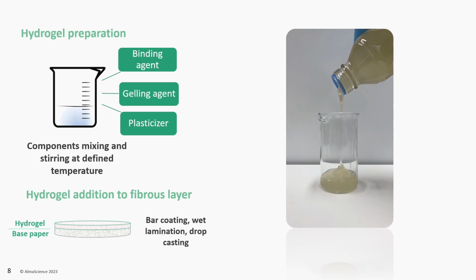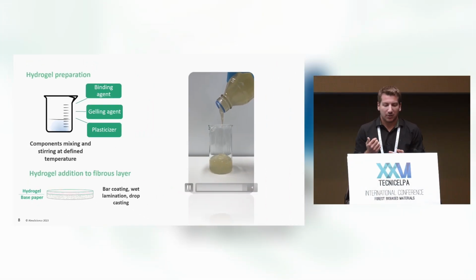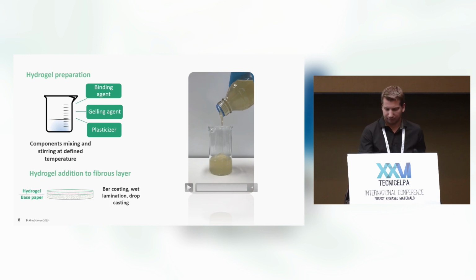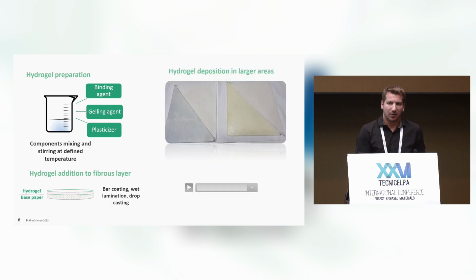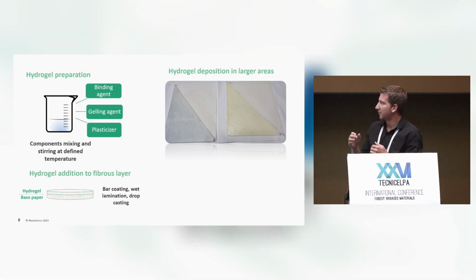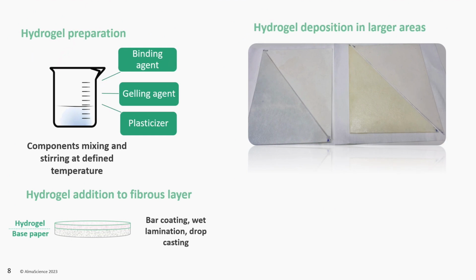But nevertheless, we could move on to the addition of the hydrogel to our fibrous layer, to our paper. We use mainly 3 methods: bar coating, wet lamination, and drop casting. I will talk a little bit about that later. By using these methods, we are able to also deposit this hydrogel in larger areas, so A4 sheets, or in some cases even a little bit bigger. Here in this picture you can see some of that.